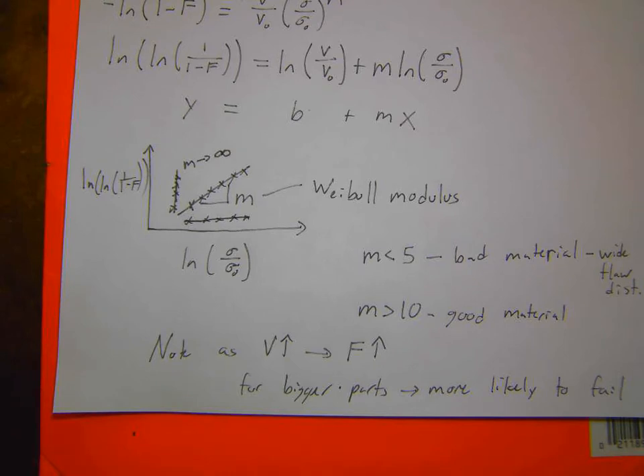And that's because you're reducing the size of the part so much that there just can't be any flaw bigger than a certain size in it. And so you get something that's close to that theoretical strength. Now, the reason this is interesting is because this is the stuff that I do. So we actually make nanostructures. We have a nano 3D printer here on campus, actually down in the WNF, the Washington Nanofabrication Facility, the clean room. And we make particularly lattice structures out of these ultra-thin films.